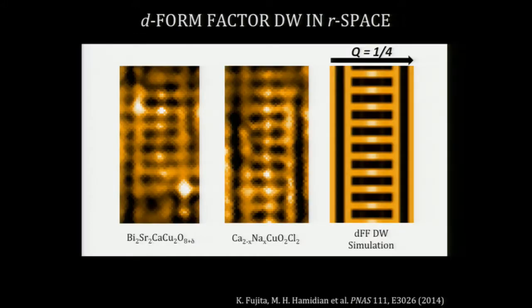Well, what we really found out, and Subir was the first one to propose that in fact these objects could be what we call a D-symmetry density wave, or a D-form factor density wave. They are ones in which, if you look at the oxygens in this direction and then look at the oxygens in this direction, they are modulating in antiphase. So one is going as a cosine, and the other one is going as a negative cosine. So the modulations are actually exactly out of phase with one another.